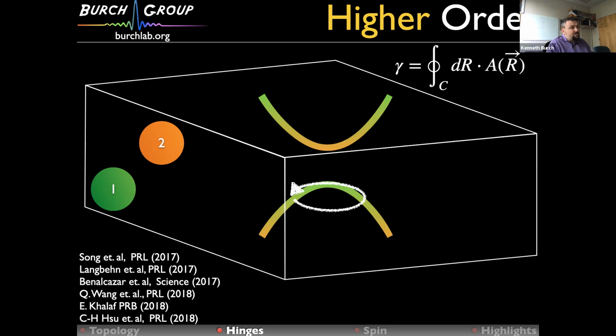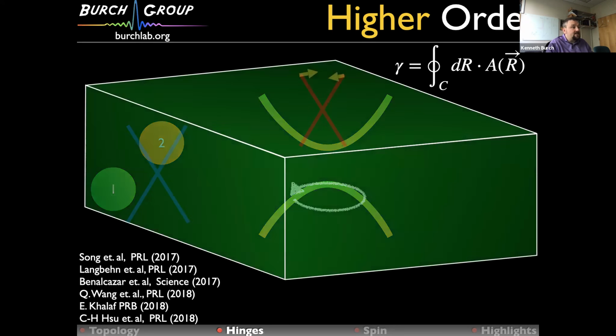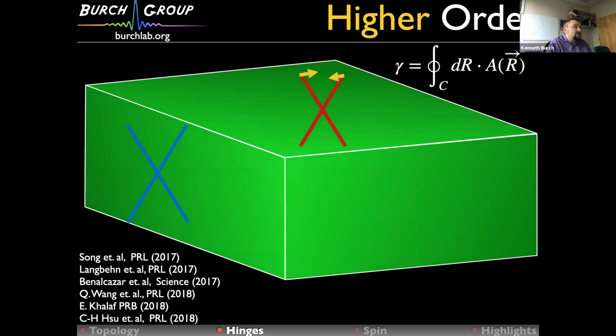If I had broken inversion, then what I would have done is made a ferroelectric. And in fact, it turns out you can model ferroelectricity with Berry phases. I'm not going to talk about that, but it works. But if I had a ferroelectric, I would expect charges at the end of my dipole. And the equivalent here, what I get instead, are surface states, these metallic Dirac-like surface states that show up on the surface of a topological insulator.